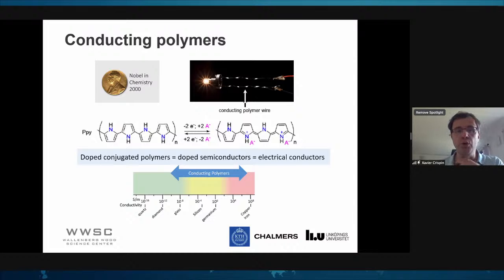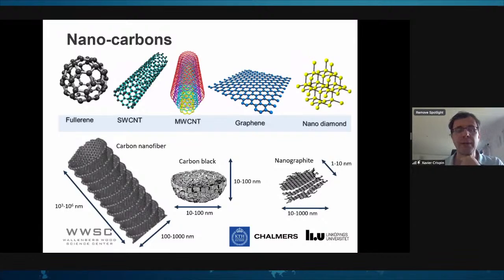Another type of conductor, nanocarbons, are all these abundant families of carbons, like fullerene, single-wall carbon nanotube, multi-wall, graphene, nanodiamonds, as well as the kinds of carbons that are larger, at the mesoscopic scale, like carbon nanofibers, carbon blacks, nanographite, that we are talking a lot about today. So those are larger-size entities that could also be very useful. Carbon black and activated carbon are very much used in battery technology because they're super cheap and they're quite small. Carbon black is something like 100 nanometers in diameter, and it's composed of an amorphous part as well as graphitic parts.